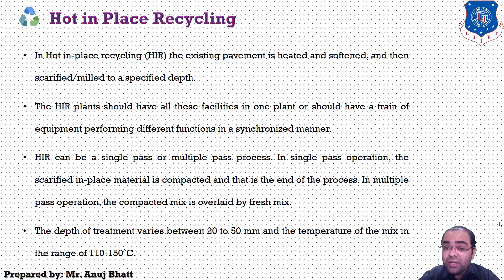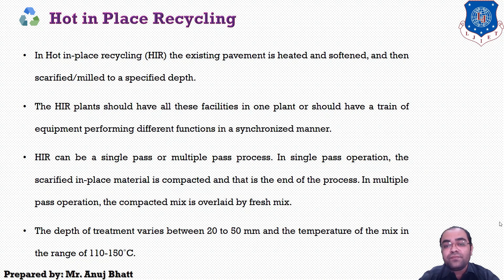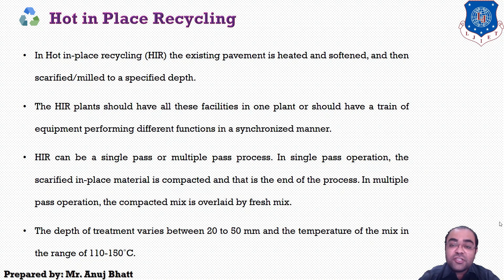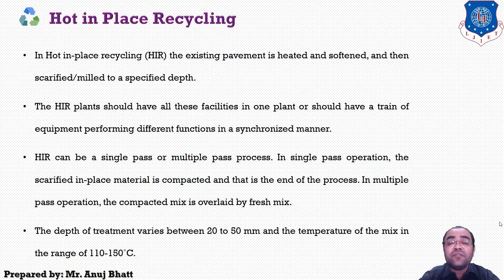Similarly, where fresh mixes are added, the rejuvenator input quantities have to be controlled. Hot in-place recycling can be a single-pass or multiple-pass process. In a single-pass process, the scarified in-place material is compacted and that is the end of the process. In a multiple-pass operation, the compacted mix is overlaid by fresh mix. The depth of treatment varies between 20 to 50 millimeters and the temperature of the mix is in the range of 110 to 150 degrees Celsius.